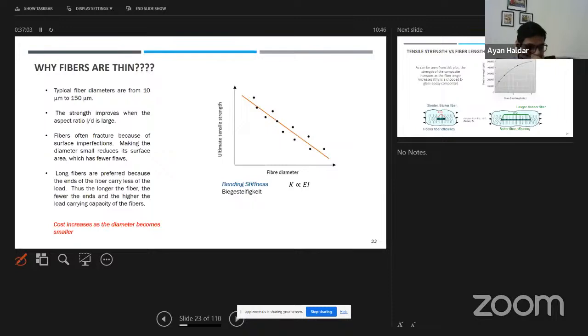Naturally, you might ask why not increase the diameter? If you increase the diameter, your bending stiffness also increases, so it should offer more stiffness against flexure, and even more tensile strength. The reason is something called the size effect. If you increase the diameter of the fiber, your ultimate strength, as you see in this figure, basically falls down. This has been observed long back.